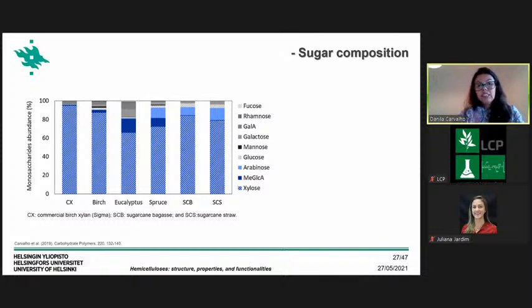The first analysis that we did for the biomasses was the chemical characterization. And here we just confirmed that the main component in the samples was the xylan. Of course, we still have some other components, probably from pectins and other hemicelluloses, but the main component was the xylan. And in this study also, we included a commercial xylan just to have some reference. And of course, the commercial xylan was much more purified than the xylan that we could get using the alkaline condition.